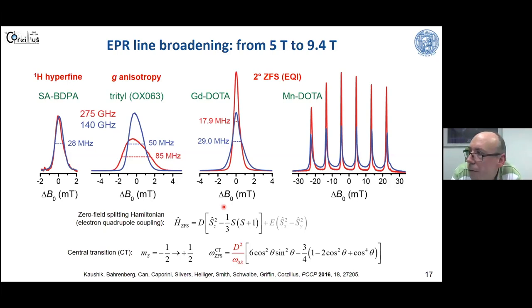I have neglected this for the moment because I want to focus on the high field case, where usually, in these cases where we are operating, the zero field splitting constant is rather small with respect to the Zeeman energy, and then we can, in most cases, neglect the actual mixing by zero field splitting. But of course you are right. You have to consider this if you go into the intermediate regime.